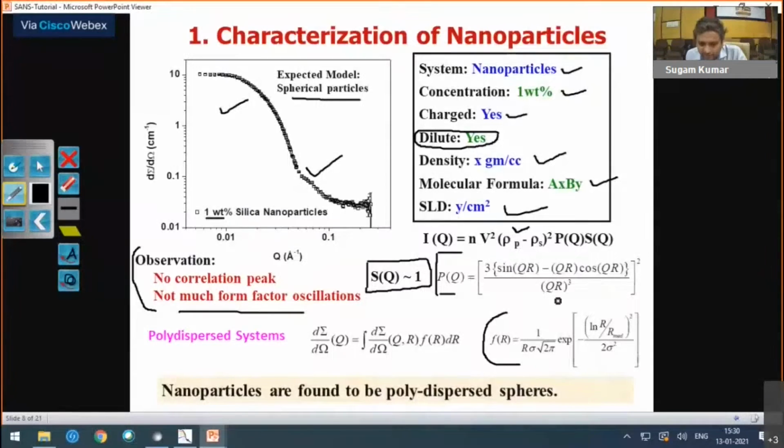So put all these equations together in this integration and do the integration to produce the theoretical curve, for the value of R such that this theoretical curve exactly matches the experimental curve with minimum reduced chi-square, using linear or non-linear least square methods. Those values of R and sigma will be our final parameters.